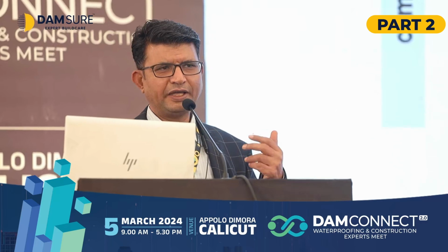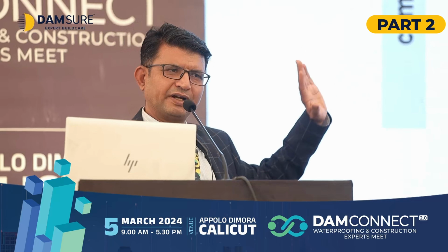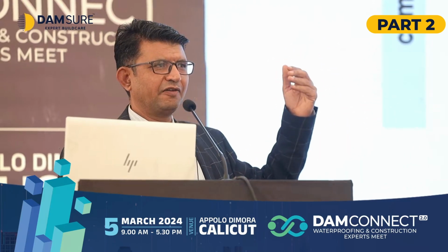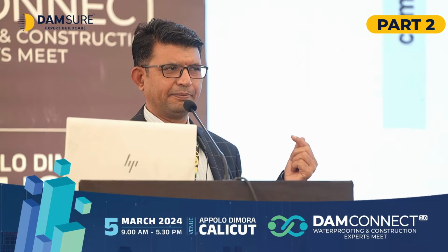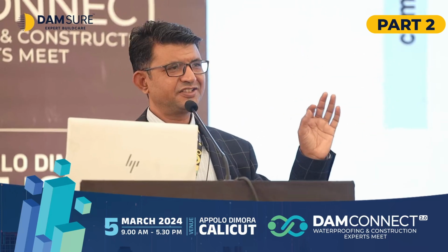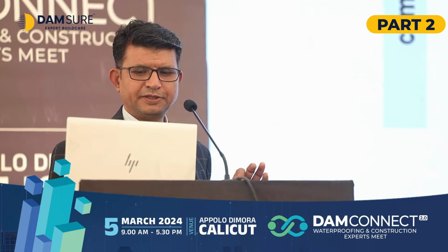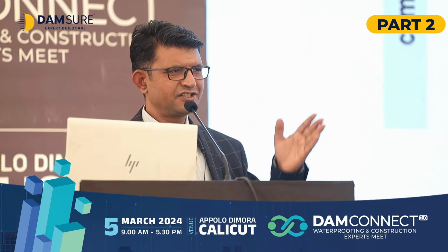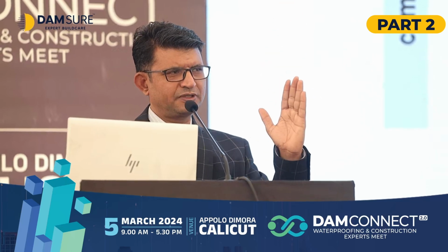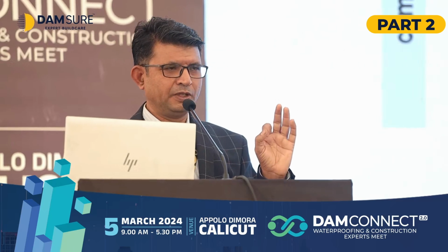So here what we are proposing is that you can go ahead with whatever methodology you are using. The only thing is that we advise you to apply one thin coat of Bactile primer, and then fix the tile the way you normally do. This thin coat helps increase the bond strength and the water resistance, because it also acts as a thin waterproof coating that stops some water migration, and it is also cost efficient in use.